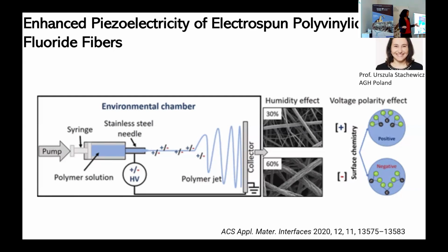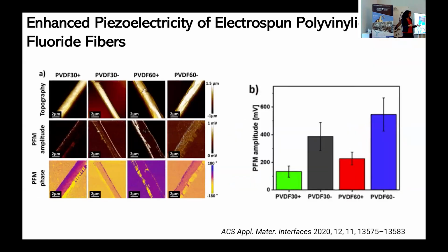But there are quite a few things that you can vary. So it's a processing technique. You can vary the temperature, the humidity, even the sign of the electric field, whether you're applying a positive bias or a negative bias. All of these have an effect on the eventual properties of the material. And this is what we wanted to find out. On the surface, if you just look at them, you probably can't tell much of a difference between, say, when you deposit at 30% or 60%. But when we start to use our AFM-based techniques to look at piezoelectric response, again, at the top here are a bunch of quite largish fibers that are produced under different conditions.